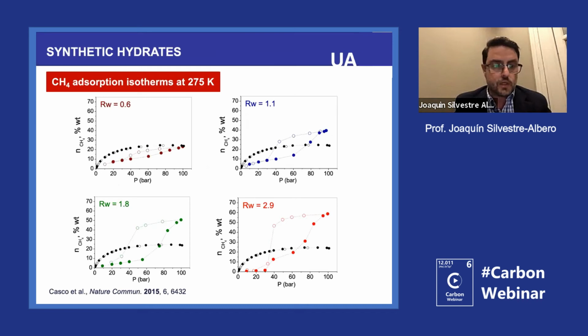And what we did is we took our carbon materials that I showed you before, and we decided to do similar experiments. We measured first the dry material, which is the black, and then we incorporated in the carbon cavities a different amount of water: 0.6 gram per gram, 1.1, 1.8, 2.9. When we were doing the methane isotherms, at the beginning we were seeing a blocking effect. So water is blocking the cavities, and that's why below 30 bars, as you can see in the red, nothing happens. But then at a certain moment, we also start seeing these jumps that I was showing before from the group of Alain.